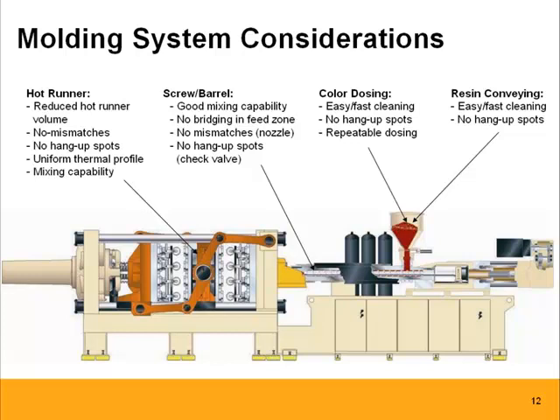In regards to screw and barrel, very important, especially if you work with smaller or organic-sized pigments, is good mixing capability. We do not want to have color concentrations that show up later on the part and slow down color change. We don't want to have bridging in the feed zones, and very important too, sometimes you have to change nozzles and other things. Make sure there are no mismatches. And of course, if you use a check valve, make sure there are no hang-up spots, and that the check valve is optimized for color change, especially if you do very frequent color changes. So look at this whole thing as a system, not just as a hot runner issue.